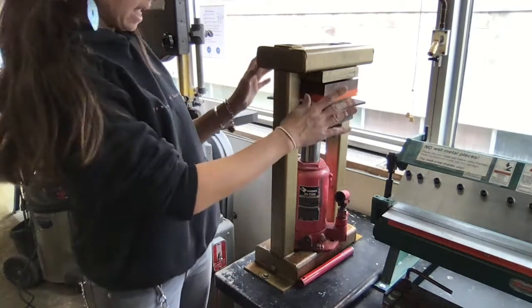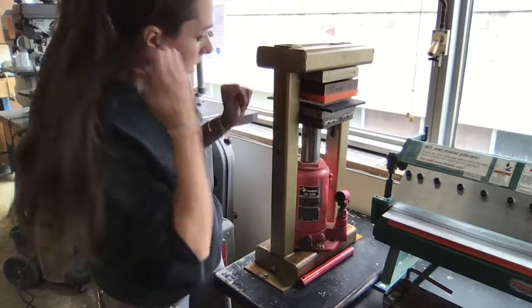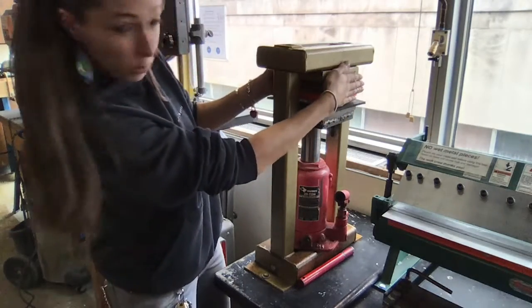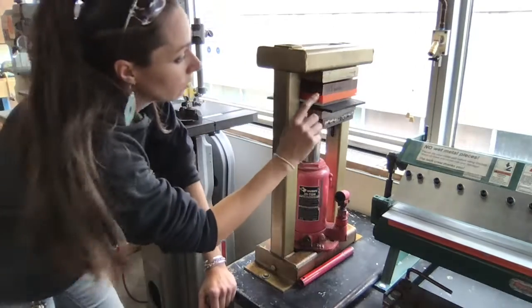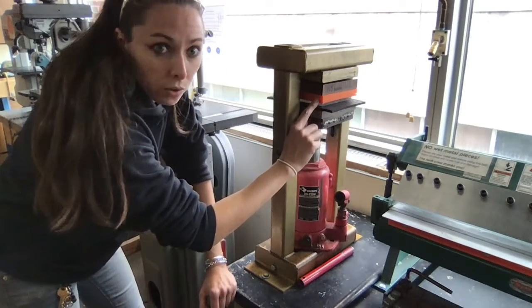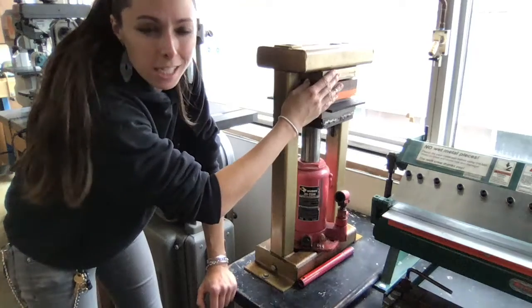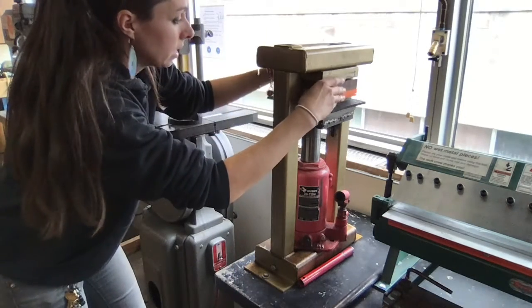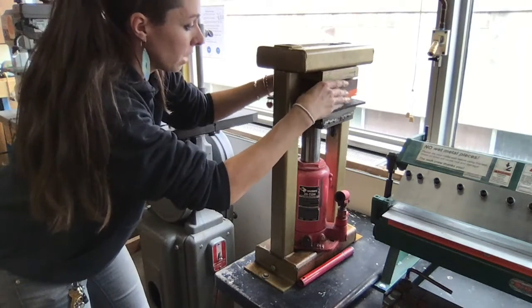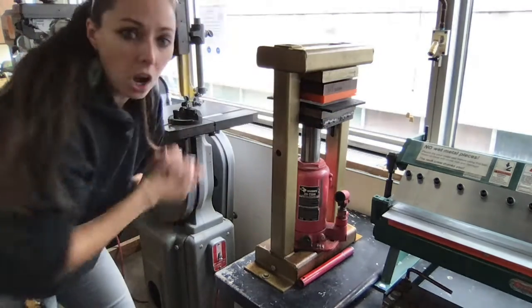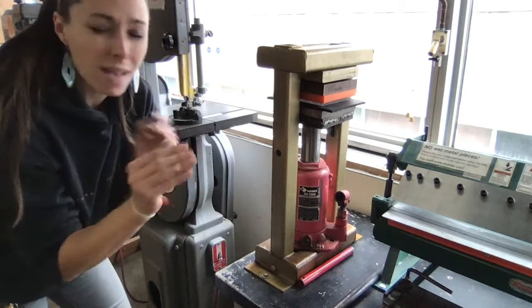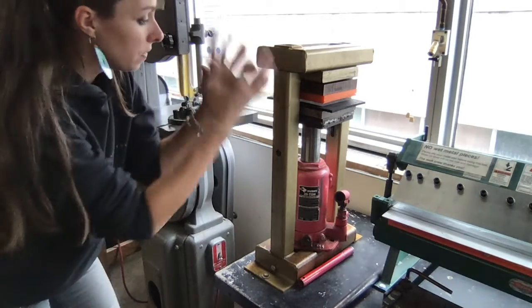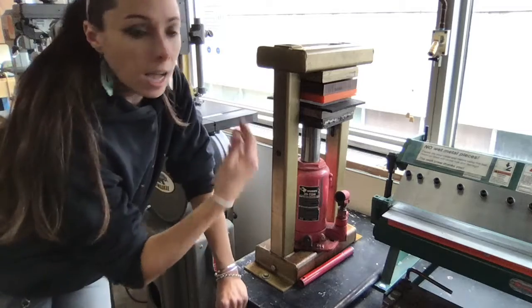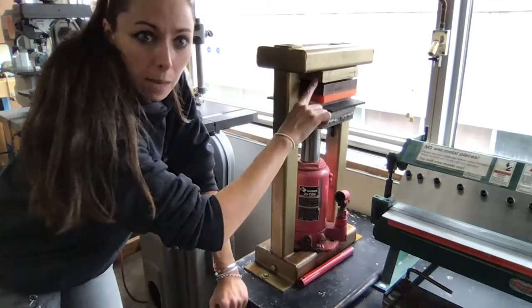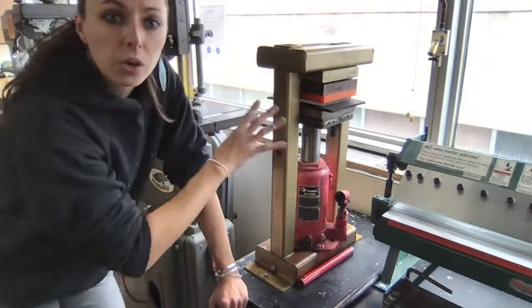And I'm going to stop right there because I want to reevaluate everything and make sure it is perfectly centered. And the reason we have 6 by 6 inch pieces of urethane is because the top plate is 6 by 6 inches. It's a really great indicator that everything is lined up perfectly because everything is 6 by 6 inches. So you want to make sure all of that's lined up, your die is in the middle, the metal hasn't shifted around at all. And this is basically where you're going to be working. This is the zone about 1/4 inch from the top plate is where you're going to be working for the majority of the operation.